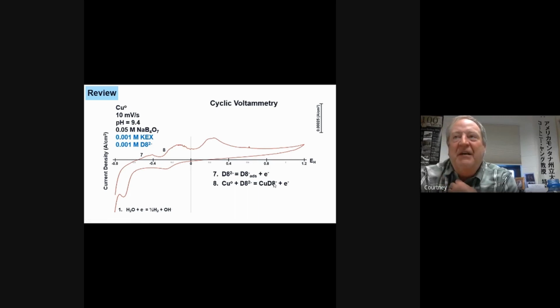I'll explain in a second. And then the next peak, you get surface precipitation. 2 of these are forming with each copper. Okay, and in each case, an electron is being given up, and you're seeing these 3 peaks, which kind of mimics the xanthate. So we're pretty comfortable with what we're seeing. But the point is that these reactions occur in the presence of xanthate. Xanthate's on the surface. All right, so we should get our hydroxide peaks back, and we do.